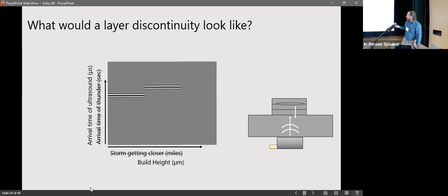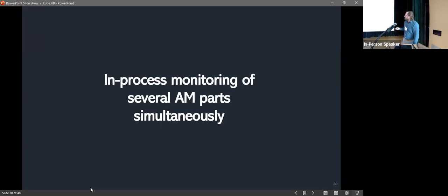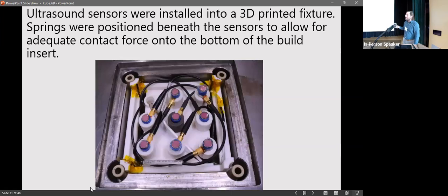So what would a defect look like? If you have delamination at one of the layers, we're going to get a reflection from that, and some of it will be transmitted through to the top surface. So it might look something like this. I'm going to show results that are somewhat similar to this in a little bit. The first thing I'm going to look at is this configuration: multiple contact transducers monitoring several parts simultaneously.